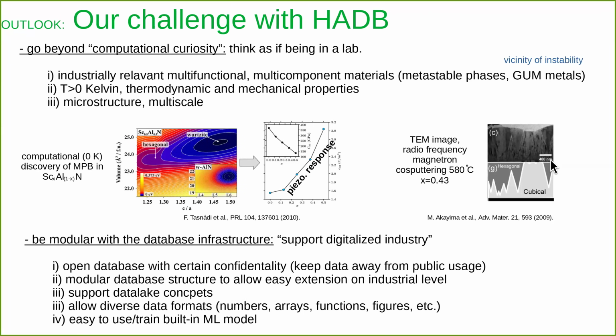So you will see a TEM image like that. On the substrate, you will have some hexagonal phase, and you will also have the cubic phase. And then if you put it into a piezoelectric force microscope, you will not see any piezoelectric response. That's because what you are actually growing, what you get out, has meaning only if you can also consider the multi-phase. So you have the hexagonal and cubic phases, the competing phases should be included, and also that was at a particular temperature and with the boundary condition.